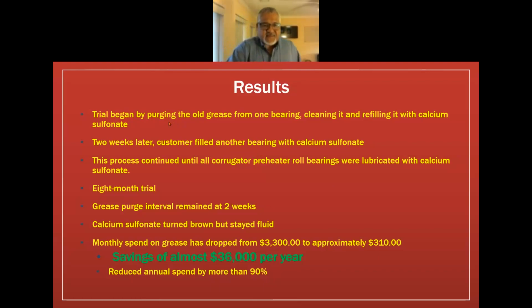So the process was to purge the old grease out, clean it, and refill it with calcium sulfonate grease. And this was while the rolls were in operation, while the machinery was in operation. That was the purging process. So it was a very, very thorough purge. Two weeks later, the customer would fill another roll with the calcium sulfonate grease.